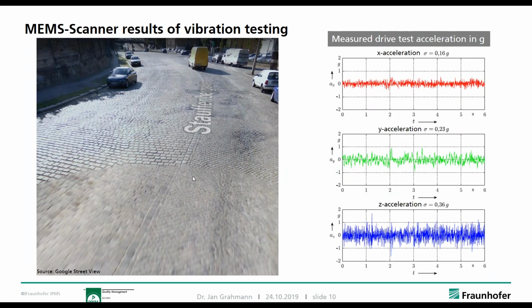So that is the road we used for that. You can just see the different bumps, and we just drove it at 50-60 kilometers per hour. And you can see here on the right side, according also to the power spectral density before, how the actual acceleration levels looked like in X, Y, and Z direction. And you can see that they are really much lower, by a factor of at least 10, partly up to 100, compared to the actual standard for testing.